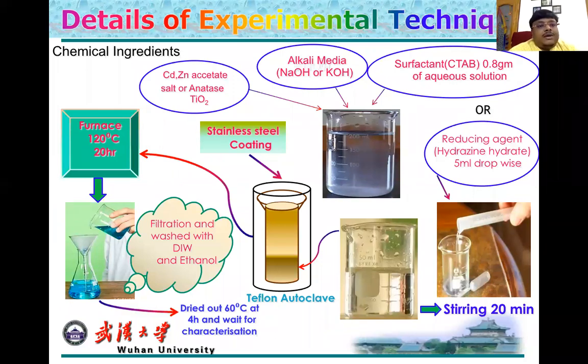So these are the chemical ingredients. We started with simple bulk powders of cadmium, zinc acetate, and TiO2, dissolved into alkaline media, and we sometimes use a surfactant for smooth growth of the nanostructure. Let's say we can utilize hydrazine hydrate, and sometimes the cationic surfactant CTAB, for the smooth and uniform growth of nanostructures, right?